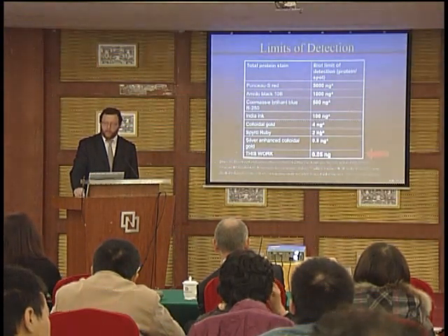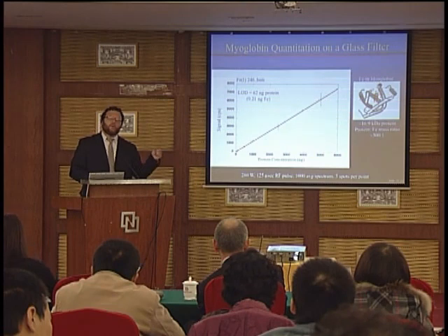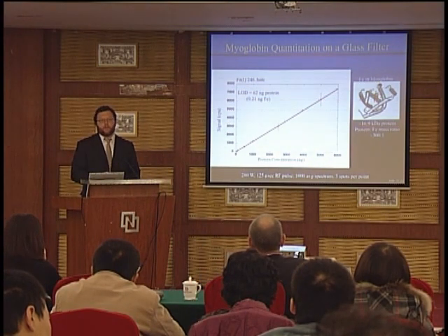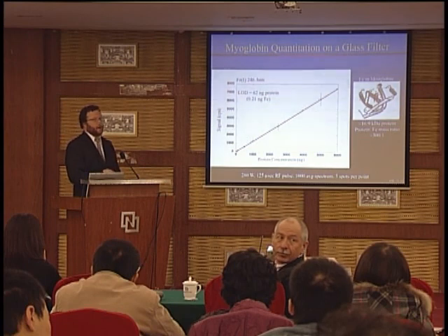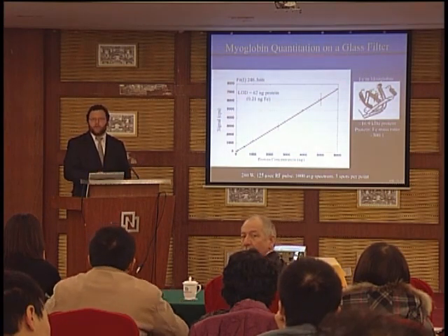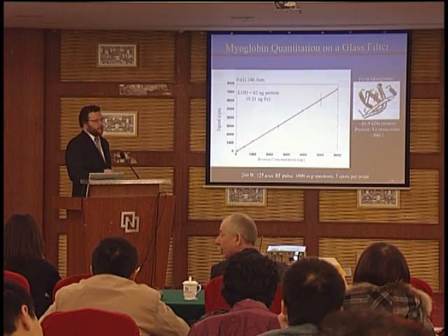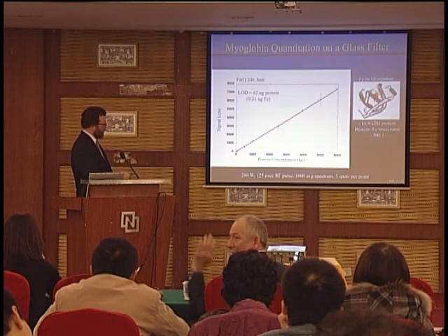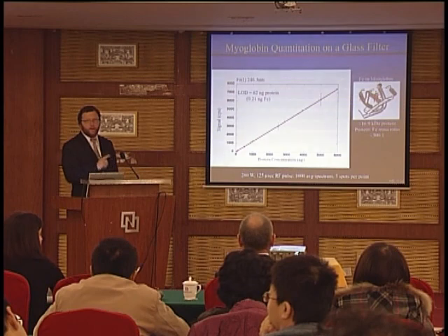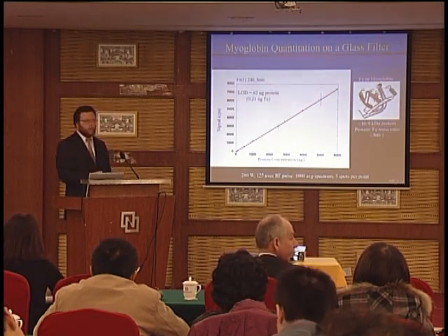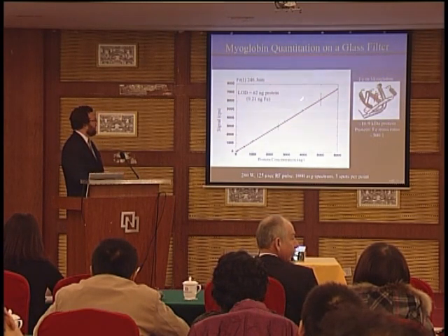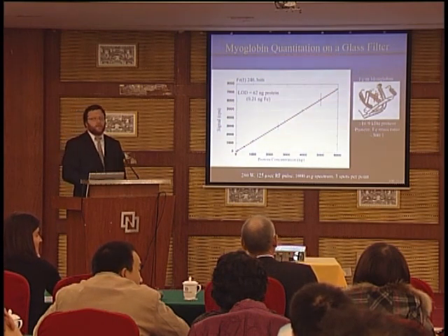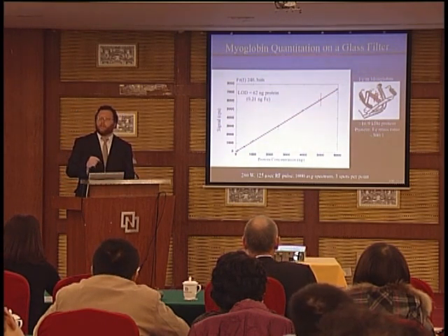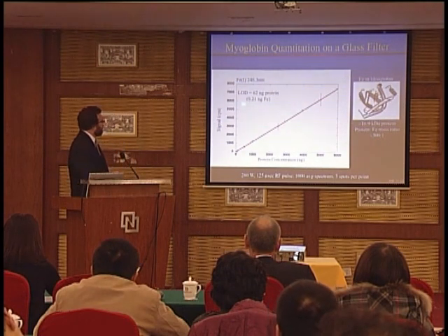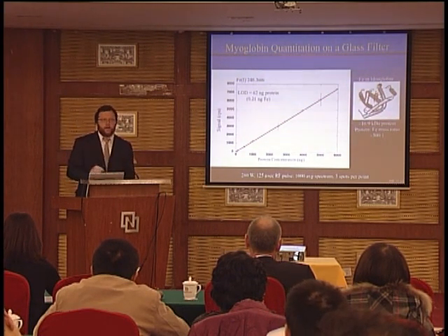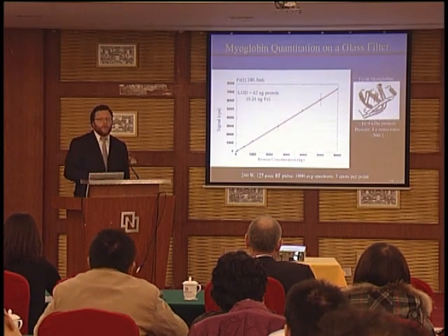But we have the added advantage that we can actually think about looking for particular elements that are within a protein of interest. So this is an example in which we've taken myoglobin, we placed it on a glass background in this particular method, and we've detected various concentrations in order to show that in fact we can get one, a linear response over a large order of magnitude. This happens to be 3 orders of magnitude. And 2, that we get very good detection and quantitation based on the stoichiometry of the protein metal complex. So here we get about 0.21 nanograms of iron as the detectable quantity, which is about 62 nanograms of protein.